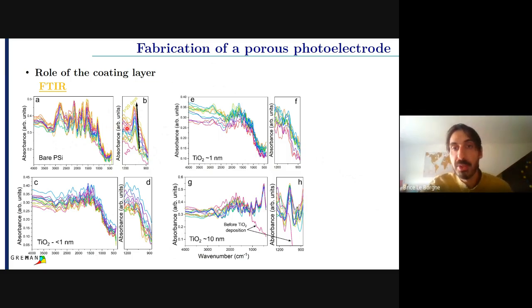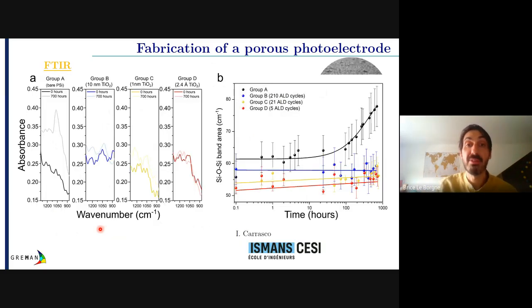So this is really documented in the literature. If you check the 1 nanometer, you can see it's not obvious to see an increase of these bonds. So I don't think it oxidizes. This is a random distribution of the absorbance, so no particular oxidation. Of course, not on the 10 nanometers. And the most interesting result here is it didn't oxidize either after 29 days with the thinnest layer, of 5 ALD cycles. So that was pretty interesting.